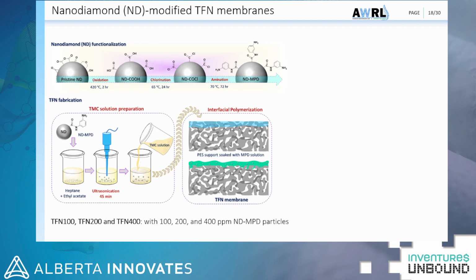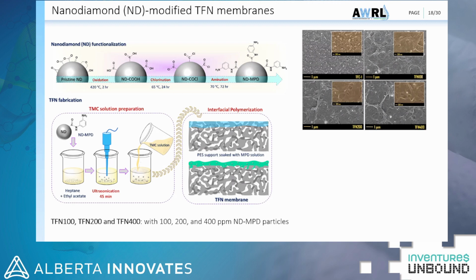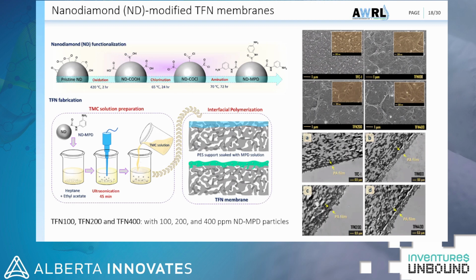We prepared four membranes: TFC1, which is a pristine TFC, and TFN100, 200, and 400, which are made by the addition of 100, 200, and 400 ppm modified nanodiamond particles. SEM showed that the morphology of the polyamide has significantly changed by adding nanodiamonds. It shows that we have nanodiamonds in the top structure. And the TEM cross-sectional images show that the formation of a thicker polyamide layer by the addition of the nanodiamonds to the polyamide layer was successful.